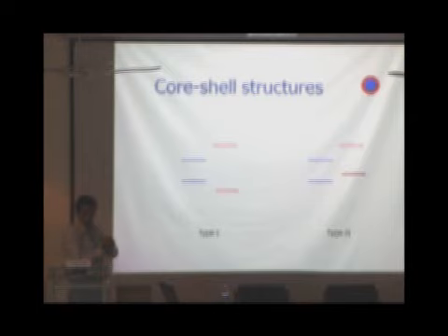Right? So once you excite it with light, you're creating this electron and hole and confining it inside. So that means they have a greater chance of recombination. So you'll get much better luminescence efficiency. So these type 1 structures are much better for use in light emitting devices. Whereas in type 2 structures, where you have such band offsets, the hole would like to float to the top over here, and the electron would stay over there. So you have separated the charges, and those structures are more feasible for photovoltaic applications.